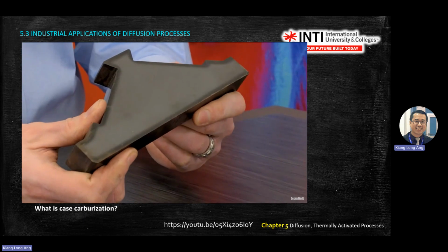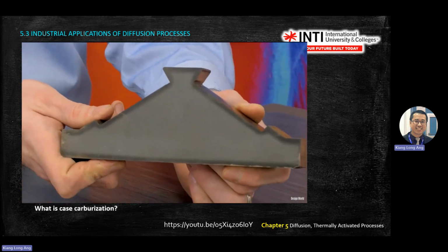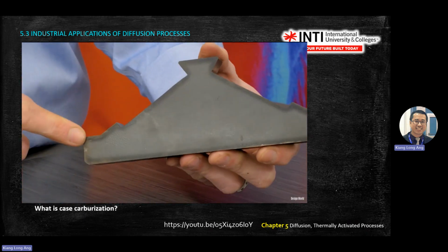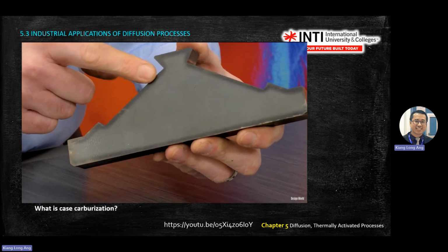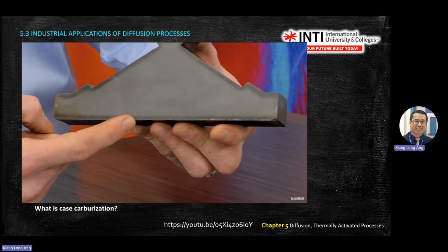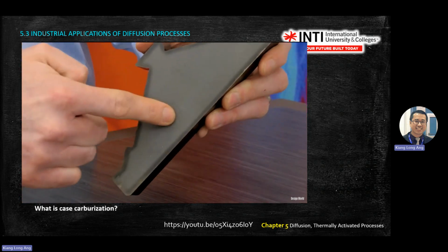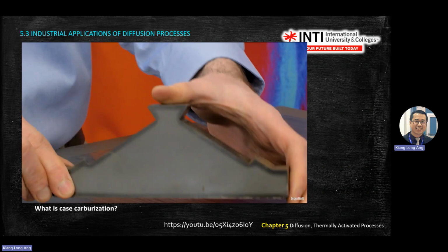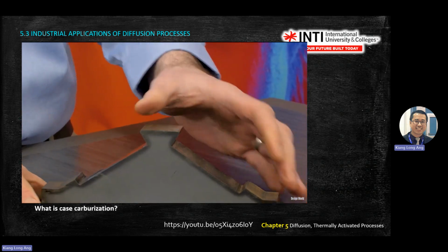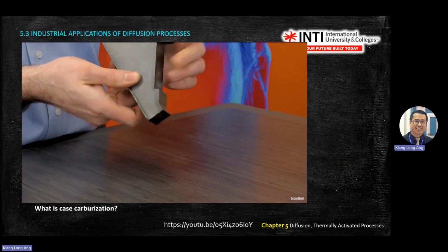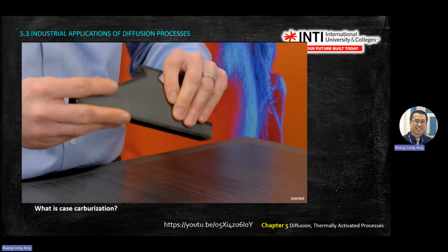It's a number of different heat treat processes. They stick it in an atmosphere. They do a carburizing process where they add the carbon into the metal, and that's what gives it its depth. For certain applications it's deeper, and for some it's really thin, depending on how the bearing's used. And then they do a quench and temper, which gives it its bearing hardness, which is usually about 58 to 60 Rockwell.